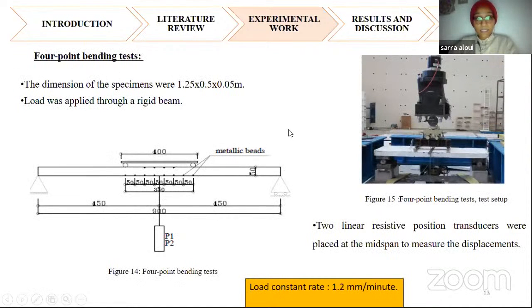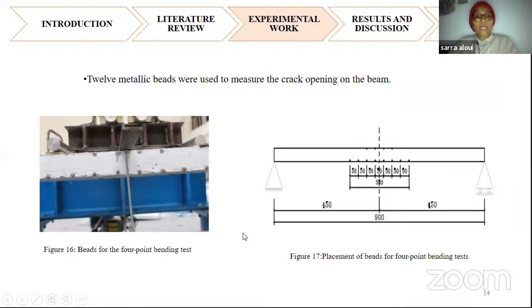The second test is the 4-point bending test, which is done after the first test. The beam that cracked at the mid-span was cut, and the half that did not see big damage was tested again in the 4-point bending test with the usage of a rigid beam, as we can see here. For this case, just 2 linear resistive position transducers were placed at the mid-span, named P1 and P2. As in the first test, we observed the crack opening by placing the metallic beads.